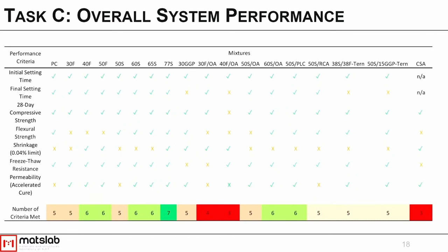So our 77% slag mixture, the mixture that had the highest amount of SCMs, actually is the only one that met all of the criteria for performance, which was actually surprising to us because traditionally there are some beliefs that there are too many challenges when you move that high in terms of strength and setting time, that we wouldn't be able to meet this, but it performed really well.